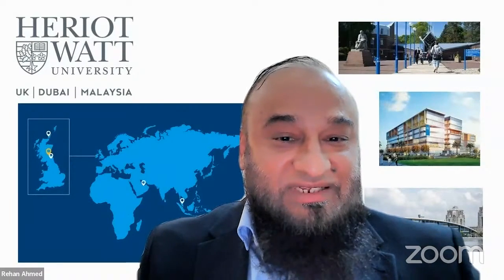Sure. One more, maybe a comment, Rihan, partly addressing Gustavo's query: one of the great limitations in this area has been material constitutive models, which have not been particularly good at predicting the heterogeneity of the materials that we produce, often through coating. You said the behavior that we usually model is continuum behavior. And the previous talk by Chris already showed the kind of microstructure variation that we get through thermal spray and other coating processes, which is often very difficult to account for in developing the material constitutive model, even with MD simulation and so on.